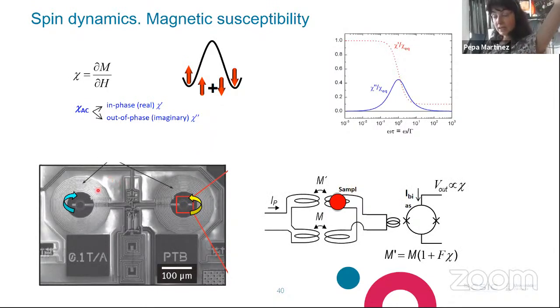So these experiments were performed with niobium microsusceptometers that I showed you in the beginning, developed thanks to the collaboration of the PTB, that consist of two main circuits. A first primary circuit creates the externally applied oscillating magnetic field, and a secondary circuit catches the signal of the sample. It's proportional to the susceptibility of the sample. This circuit is inductively coupled to the nanoSQUID, to the microSQUID in this case.